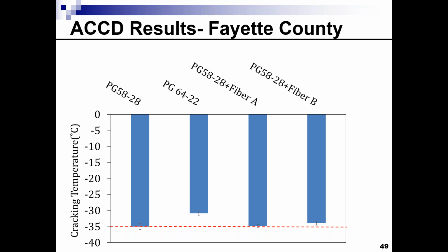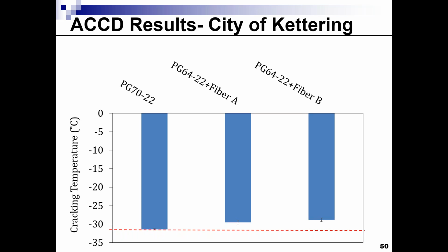So in this case, if you're using a 64-22, you're seeing a lower low temperature cracking resistance, which is something that is expected. This is consistent with what we expect. But I think the main thing here is that the fiber really did not affect the low temperature cracking, at least based on the ACCD test result.